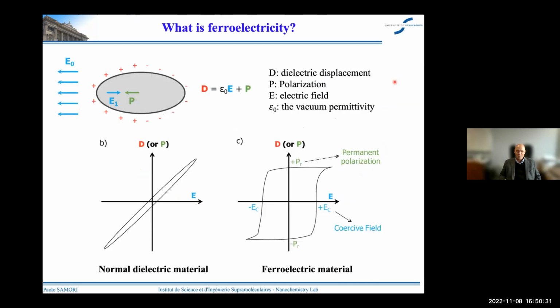Now, how does ferroelectricity work? I think most of you already know that if you apply a voltage to a ferroelectric material and this voltage is high enough to exceed the coercive field, the dipoles in the ferroelectric layer partially align with the external electric field, and this results in a permanent polarization after the removal of the electric field. The magnitude of the polarization vector depends on the difference between the applied electric field and the coercive field. So the number of memory states that can be accessed in the ferroelectric memory cell depends on the intermediate polarization states obtained by applying an external electric field with a magnitude slightly higher than the coercive field. In this way, you can access multilevel current states encoded in your material and device.